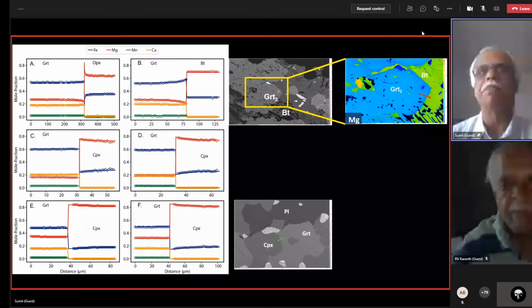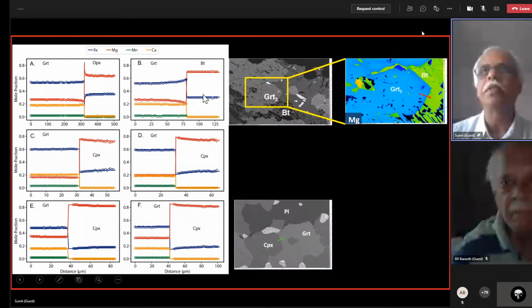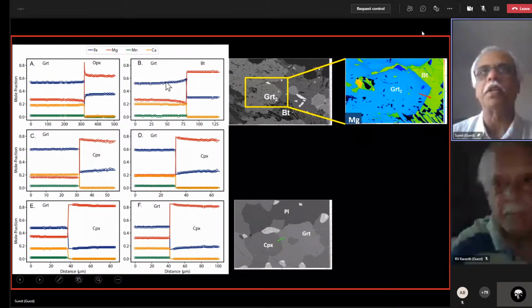So in real physical pictures, you see this is a backscattered electron image again. You see the garnet-biotite contact. So this is about where you measure such a profile. You see that the garnet is zoned and the biotite is not. That's because diffusion in biotite is usually quite a bit faster.